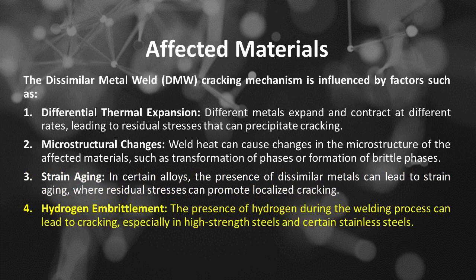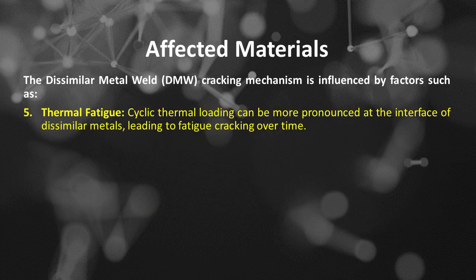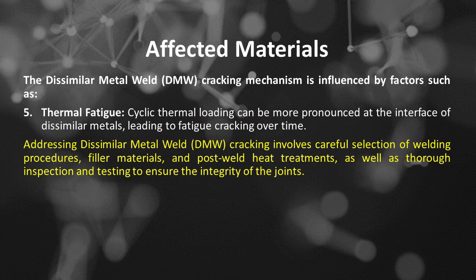Number 4 is hydrogen embrittlement. The presence of hydrogen during the welding process can lead to cracking, especially in high-strength steels and certain stainless steels. Number 5 is thermal fatigue. Cyclic thermal loading can be more pronounced at the interface of dissimilar metals, leading to fatigue cracking over time. Addressing dissimilar metal weld, or DMW, cracking involves careful selection of welding procedures, filler materials, and post-weld heat treatments, as well as thorough inspection and testing to ensure the integrity of the joints.